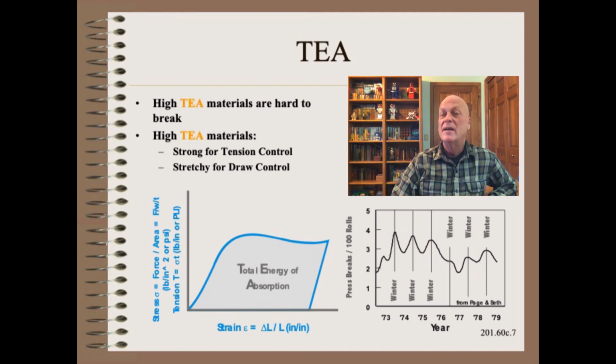Simple, because dry paper is brittle rather than ductile. In short, the TEA, modulus of rupture, and ductility all have been decreased during the dry months, completely obliterating any benefits of a stronger tensile.